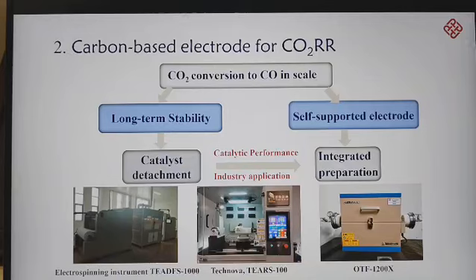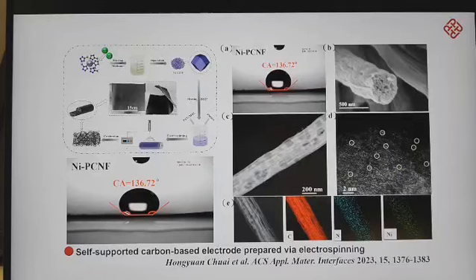To address these issues, we considered anchoring highly efficient CO-producing active sites, such as nickel-nitrogen structures, on carbon-based electrodes and developed a technology for preparing large-scale carbon-based electrodes via electrospinning. This part of our work is to regulate the pore structure of carbon-based electrodes to optimize their performance.